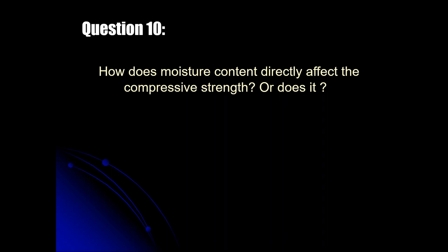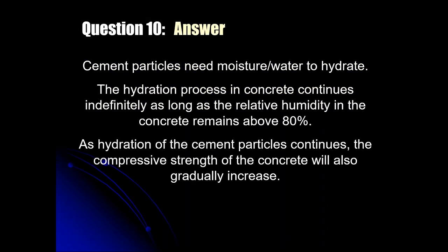Question 10. How does moisture content directly affect the compressive strength, or does it? Cement particles in a concrete mixture absolutely need water to hydrate, and the hydration process continues indefinitely as long as the relative humidity in the concrete is 80% or higher.